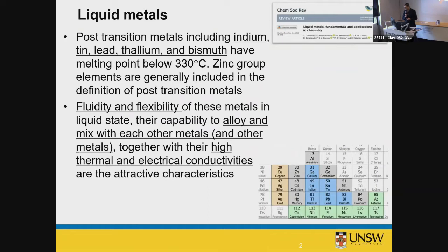Their melting point is very low. Gallium 30 degrees, tin 230, bismuth 270. We sometimes put the zinc group into this post-transition metals group definition, although something which makes them very comfortable not to, because the blue elements, the melting point is 330, but zinc is 420. Now, if you put that in, it becomes a bit distorted, the definition of low melting point liquid metals. Regardless, all these definitions and classifications are very difficult, and always there are some outliers.